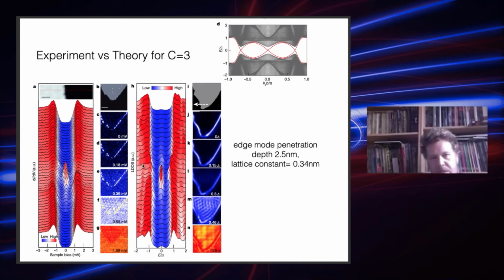There are a couple of things that are not quite seen here. In the real experiments, there seems to be a modulation of the edge mode intensity, and this modulation has the same periodicity as the Moire pattern. In the first modeling, we didn't implement the Moire pattern. There are also follow-up experiments and modeling which strongly suggest that this type of periodic enhancement and suppression is due to the Moire pattern.